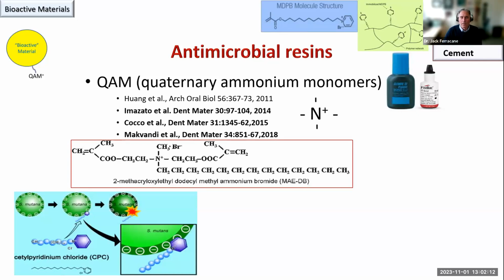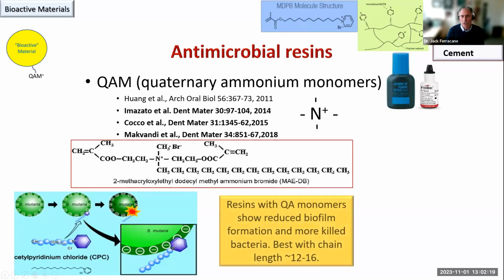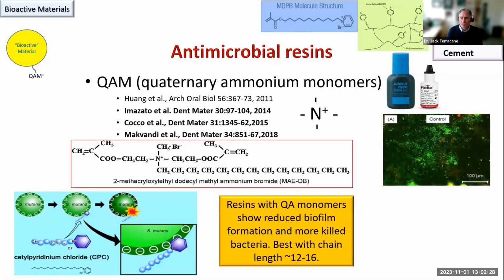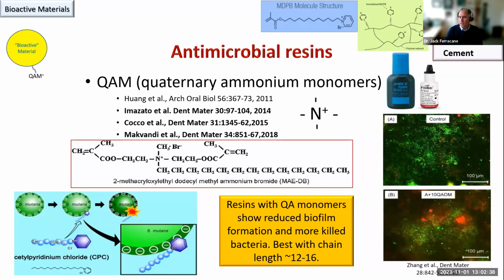And here's another example of one of these molecules with a very long carbon chain attached here. Now, this turns out to be pretty critical and shown in a number of different studies that this material is most effective when this chain is about 12 to 16 carbons in length. This is just the depiction of a live-dead assay of biofilm on a surface of a control material, green meaning it's pretty happy. And here it is on the surface of one with a quaternary ammonium at about 10%, showing a lot of dead bacterial cells.